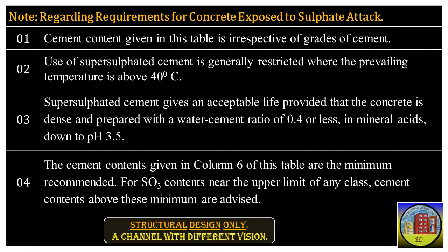Below Table 4, there are 7 important notes regarding requirements for concrete exposed to sulfate attack. They are as follows. Note 1: Cement content given in this table is irrespective of grades of cement. Note 2: Use of supersulfated cement is generally restricted where the prevailing temperature is above 40 degrees Celsius.